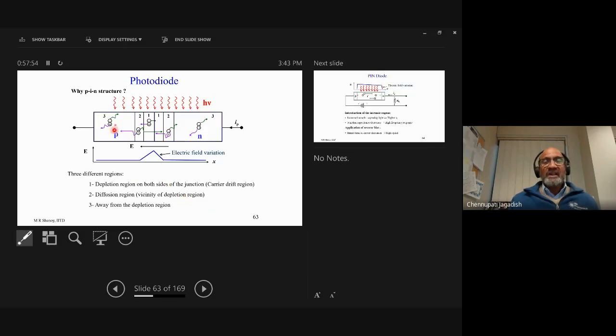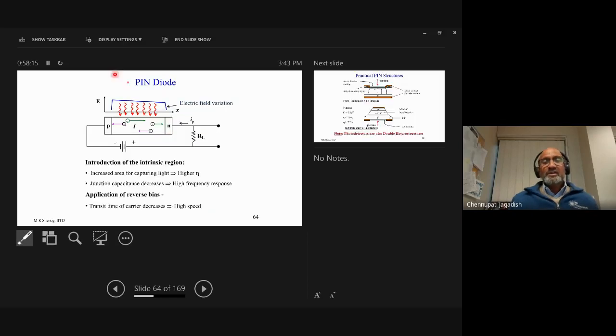So here is a case where you have a standard PN junction. This shows the electric field distribution in the depletion region. And then you have the drift region and also the diffusion region and various things which I will not have time to talk about. The key thing is that you're shining light and reverse biasing it, and then extracting the carriers. By introducing the intrinsic layer, the volume of material you're shining light on increases. That means you're able to create much more efficient photodiodes, and you can also control the junction capacitance by controlling the thickness of this intrinsic layer. Particularly if you want to make high-speed devices, reducing the junction capacitance plays an important role, and that's why people use these.